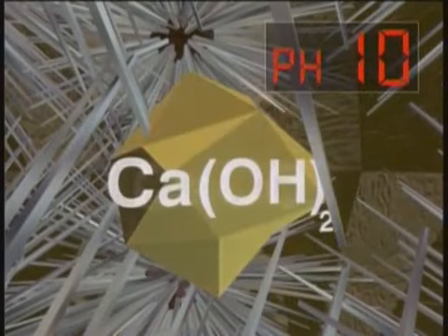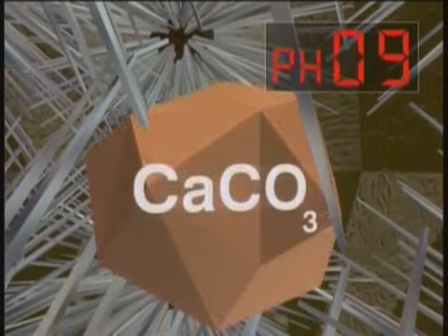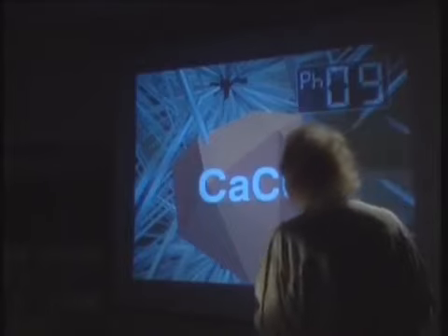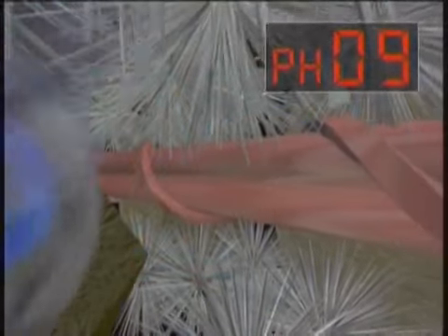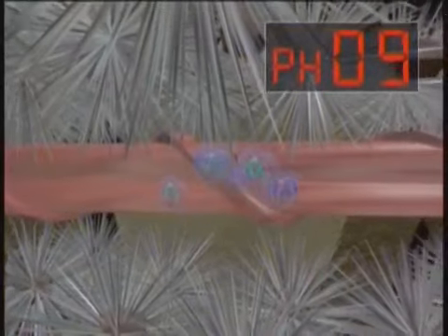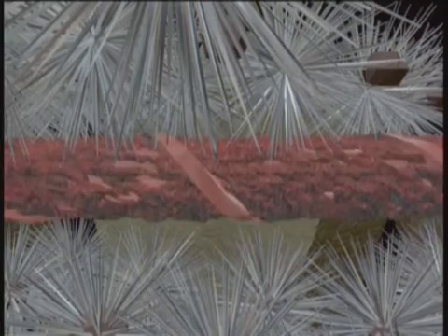When the carbon dioxide present in the air penetrates into the concrete, it reacts with calcium hydroxide and neutralizes it. There is a lowering of the basicity of the environment. And with a pH below 11, the steel reinforcing bars inside the carbonated concrete are no longer protected. From the outside, water and oxygen also penetrate, thus increasing the rusting reaction of the reinforcing bars.